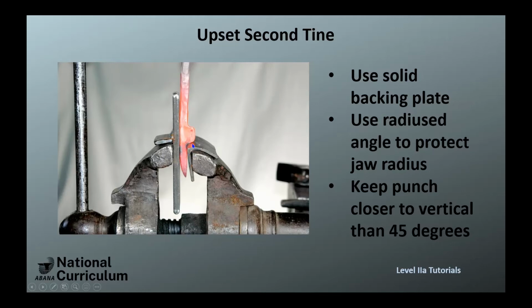You can't tell, I think the radius is a little bit more than what it's showing right here, but you don't want to get a cold shut right there because you have a sharp edge, which is what your vise may be giving you. And your vise is also going to be typically less than 90 degrees, so that angle might be getting too sharp.